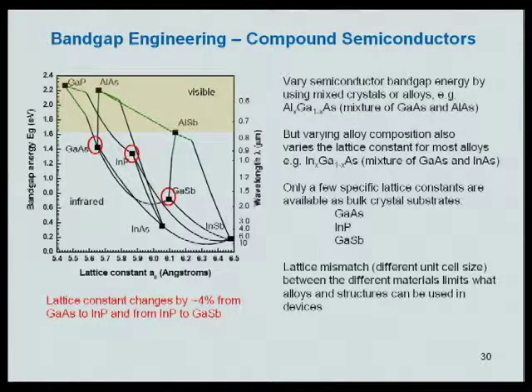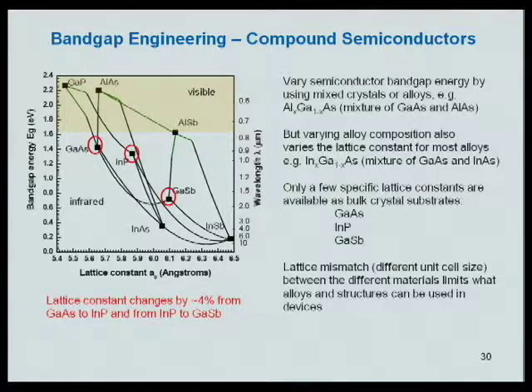For example, if we mix gallium arsenide and aluminum arsenide, there's a very small change in lattice constant, but a very, very large change in band gap depending on what the fraction of aluminum arsenide in the crystal. On the other hand, we can reduce the band gap by mixing gallium arsenide and indium arsenide, but when we do that, we also find that the lattice constant of the crystal changes as well.